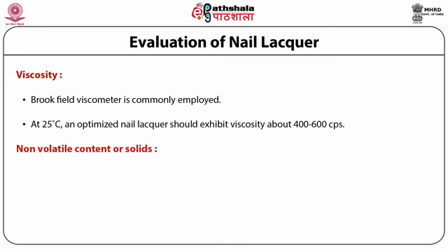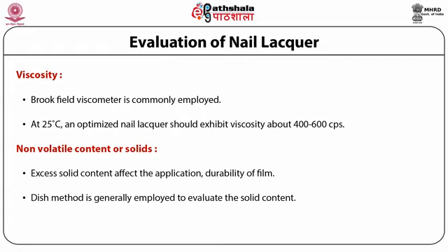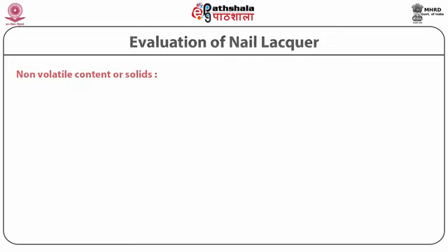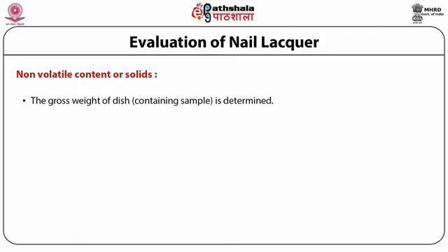Non-volatile contents or solids. Excessive solid content affects the application and durability of the film. The dish method is generally employed to evaluate the solid content. About 1 to 2 grams of lacquer is poured into a tared dish having a diameter of about 2.5 inches. The gross weight of the dish containing the sample is determined.